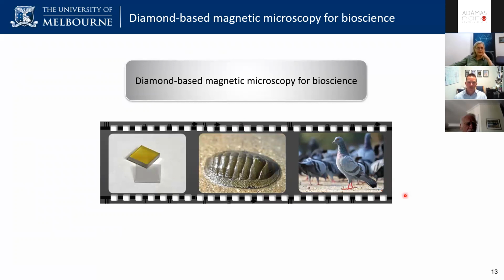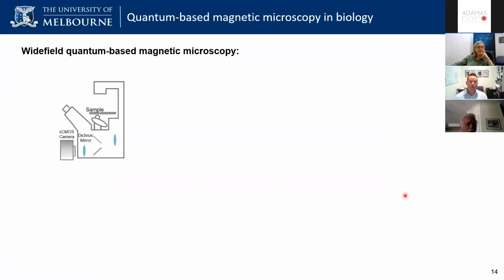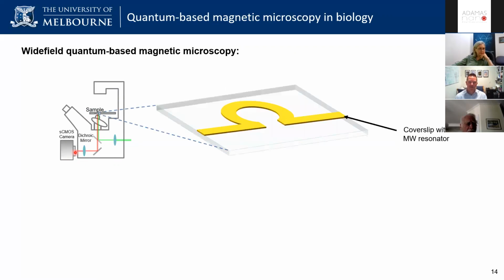So before I do that, I'll just tell you quickly about how we perform magnetic microscopy using these single crystal diamonds. So now we're building these wide field microscopes that have our green excitation coming in. We shine that onto these single crystal diamonds which contain NV centers, and we image the fluorescence onto a sensitive CCD camera. And in terms of the samples that we're working with, we typically start off with a glass cover slip. We pattern a microwave resonator. Onto that, we put a thin